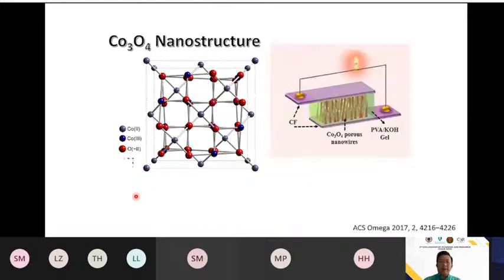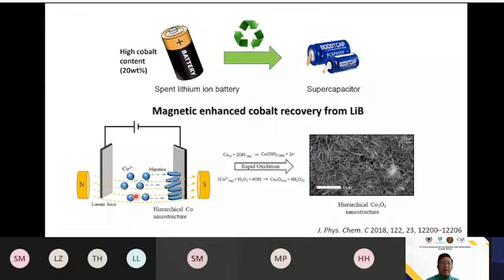Then we turn to another metal oxide, which is the cobalt oxide nanostructure. For the cobalt oxide nanostructure, we form it into a supercapacitor as well. Then we start to think of where we can get the cobalt. We look at other types of battery, the lithium-ion battery. Every piece of lithium-ion battery actually contains cobalt, because the lithium that we use in the lithium-ion battery is in the form of lithium cobalt oxide. So every piece of lithium-ion battery contains a high cobalt content, which is 20%.